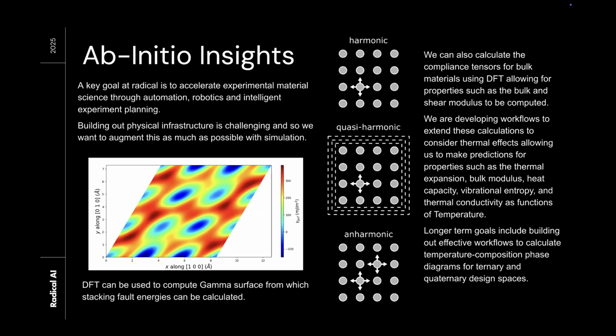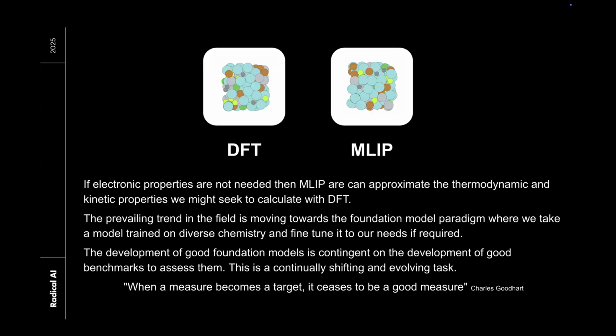The other things that we're doing are taking conventional bulk property assessments and extending them both to the quasi-harmonic approximation and the anharmonic approximation, and looking at the temperature dependence of things through simulation rather than just the 0 Kelvin bulk modulus, for example. And then this brings us to ML within our material space.